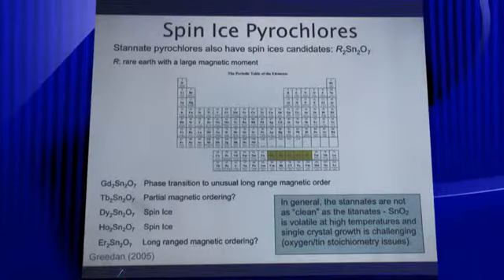But looking at powder samples, people have determined that dysprosium and holmium are spin ices, and terbium stannate is not a cooperative paramagnet, but people believe it actually has a partially magnetically ordered state. So in the stannates, these are the only two known spin ices throughout that whole series.